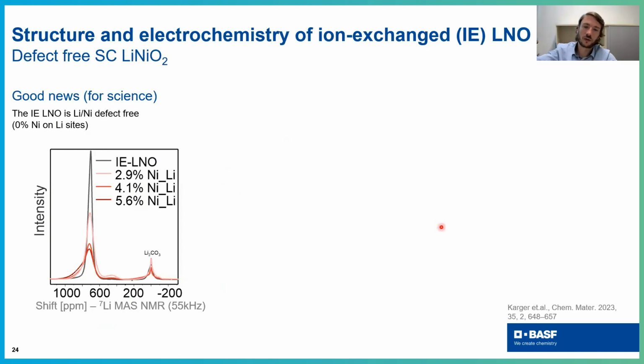And now if you characterize this material, first, what is interesting to see, we are talking about lithium nickel exchange, and it is very interesting to do NMR, which was done here by a group of Silvio Indris, where you compare your ion exchanged LNO sample with the conventional LNO samples made by solid state synthesis, where you go to really high temperatures. And these samples, they are here in red. They have different lithium to nickel exchange from 2.9% to 5.6%.